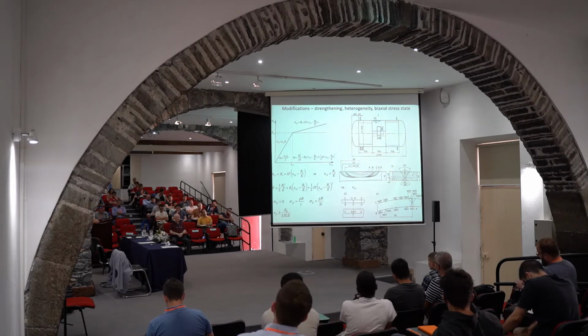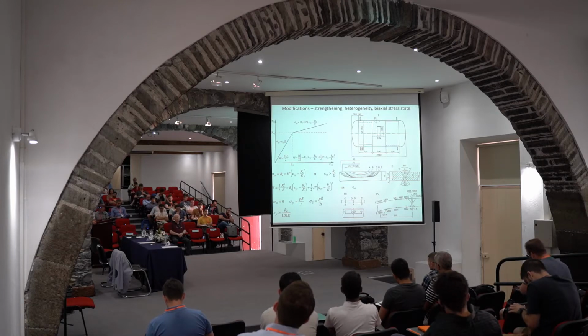But we can also do something more direct. We can measure J integral on the pressure vessel if we apply this modification of direct measurement of J integral. It is relatively complicated, and not surprisingly people are not often doing it, but what we did in these experimental investigations decades ago was to cut out one piece of the pressure vessel containing weldment, then make an artificial crack in that piece, and then weld it back to the pressure vessel.